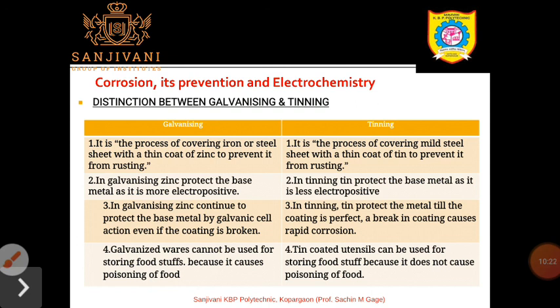In galvanizing, zinc continues to protect the base metal by galvanic cell action even if the coating is broken. Means all the time the zinc protects the base metal. But in tinning, the tin protects the metal only as long as the coating is perfect. A break in the coating causes rapid corrosion. And the last one, galvanized ware cannot be used for storing and preparing foodstuff, whereas tin coated utensils can be used for storing foodstuff because it does not poison the content.